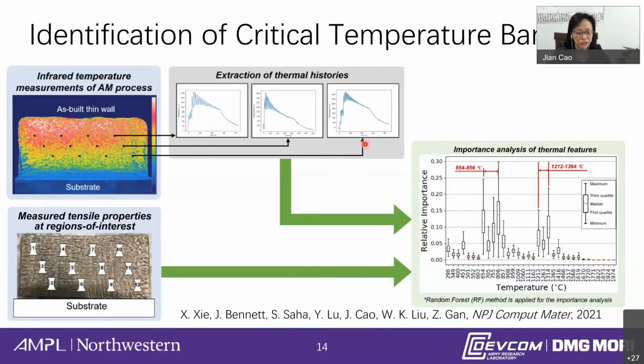each temperature, we separated it into about 50-degree intervals. So all these are 50-degree intervals, and the y-axis is the relative importance of how the time spent at that temperature range influences the mechanical property. So when you look at this, it came out to be actually two zones. This zone and this zone, as you can see, have the highest relative importance.